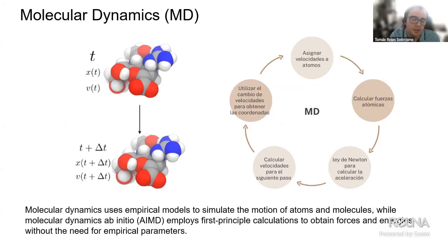We use a first guess for assigning velocities to the atoms. We calculate acceleration and forces based on those velocities. And using Newton's law, we calculate the velocities for the next step in time. And we do that in a cycle until we are satisfied with how long the calculation has run. Classical molecular dynamics can run for scales of nanoseconds and can easily simulate nanometers